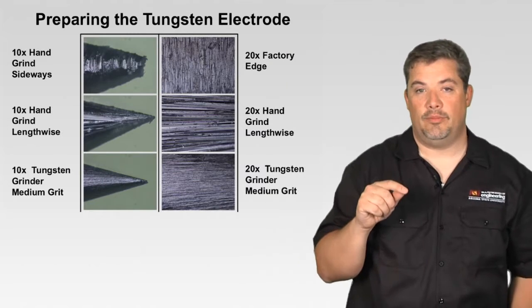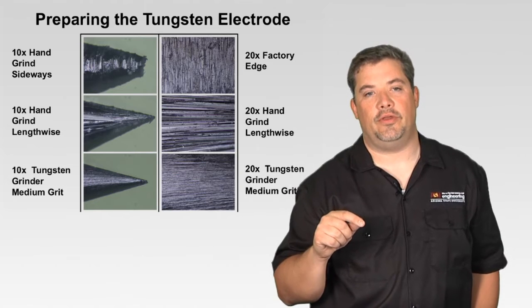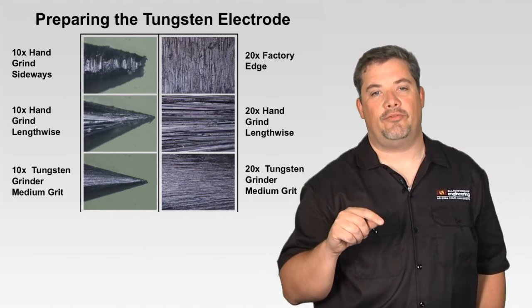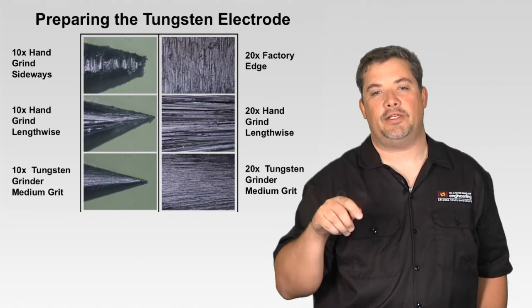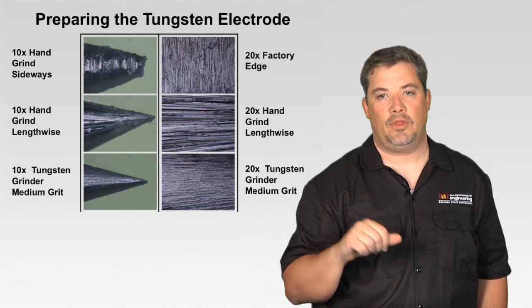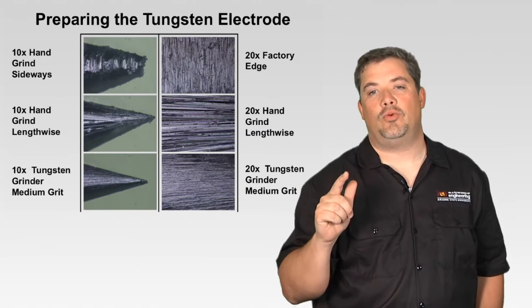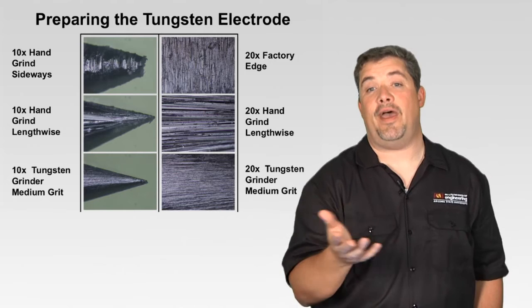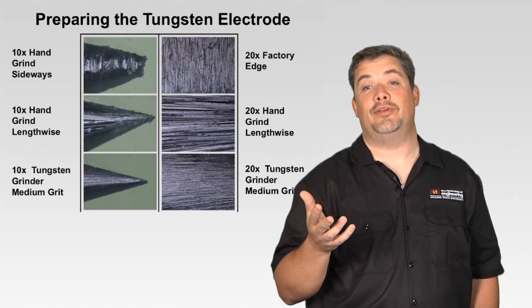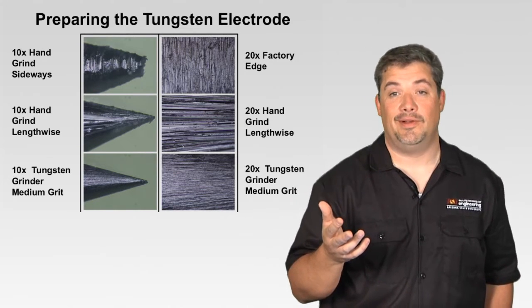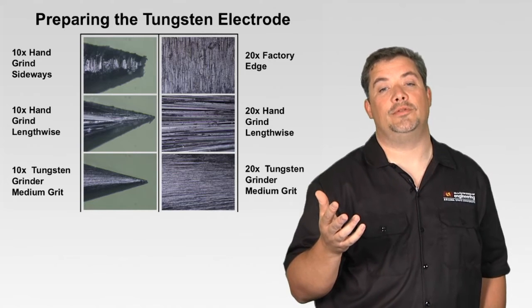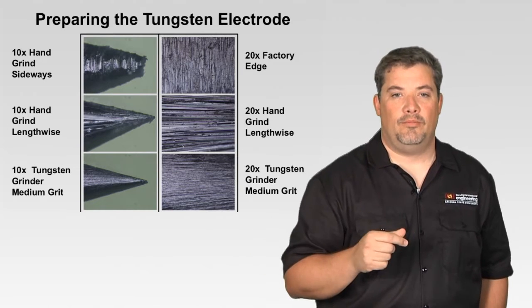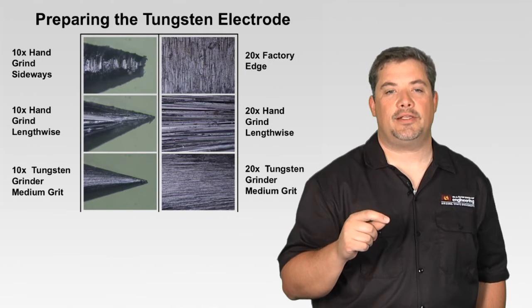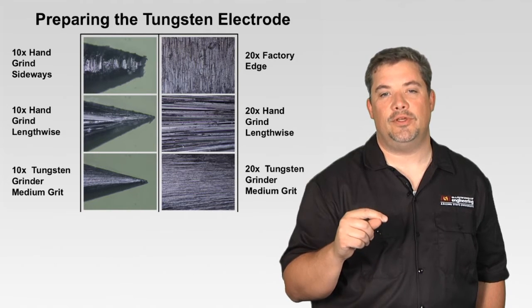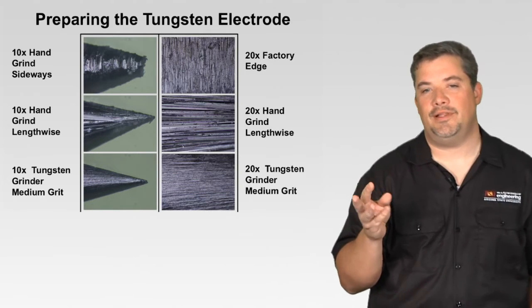So here's another good illustration. You can see 10 times in the upper left corner. That's a 10x magnification of hand grinding it the wrong direction. On the right top is a 20 times magnification of the factory surface. So the factory surface is even ground in the wrong direction, but it's at least pretty smooth, so it helps. The next middle picture down on the left, 10x hand grind lengthwise. So you can see, if you look close there, you can see a lot of burrs and things.